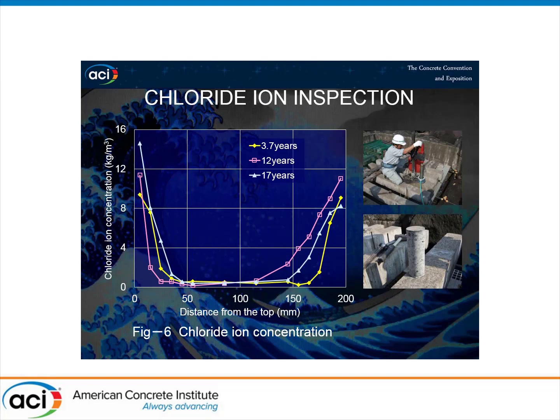In this study, the chloride ion concentration of concrete exposed in the splash zone was inspected at the ages of 3.7 years, 12 years, and 17 years. This figure shows the measured chloride ion concentration. The left side is the top of the section and right the bottom. The chloride ion concentration was measured over 5 kilograms per cubic meter at the tendon located 35 millimeter from the surface of the specimen,